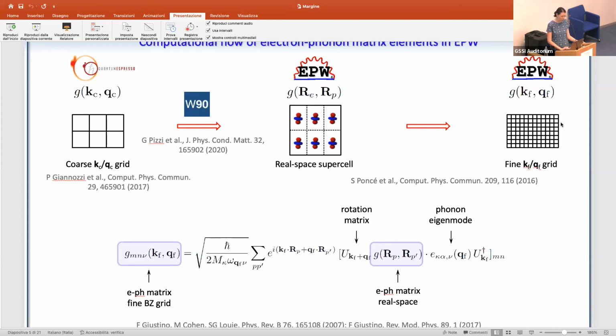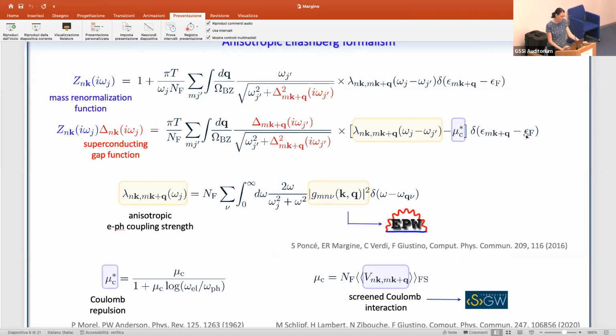Once you have electron-phonon matrix elements, you can calculate a number of properties with EPW, among which you can solve the anisotropic Migdal-Eliashberg equations. So in this case, these are the two equations in what is called, a few papers have referred to this as, the Fermi surface restricted approach, because these two equations are obtained under the assumption that the superconducting pairing mechanism takes place within a small window around the Fermi surface, and the density of states at the Fermi level is assumed to be constant. In the current version of the code, they have also gone further and implemented the full bandwidth description, but that has not been used in this study.